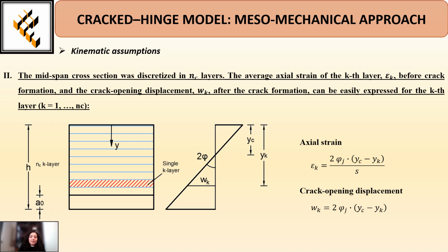Then, if we discretize the mid-span section in NC layers, we can evaluate as follows the average axial strain of the kth layer before crack formation and the crack opening displacement after crack formation. It means that the average value of the axial strain of the concrete at the kth strip can be determined as a function of the axial deformation before cracking, or a function of the crack opening displacement after cracking.